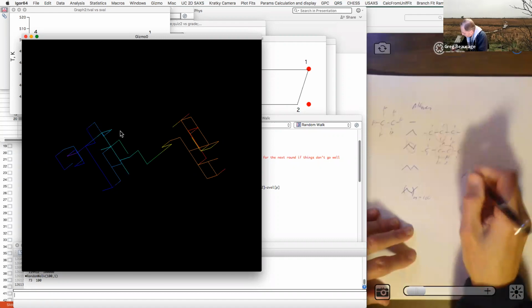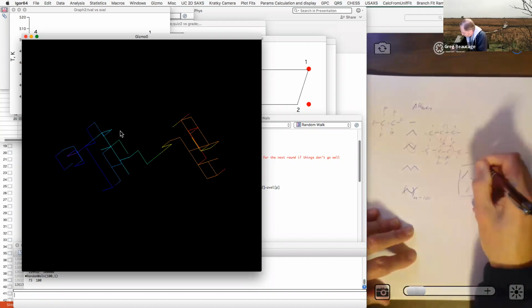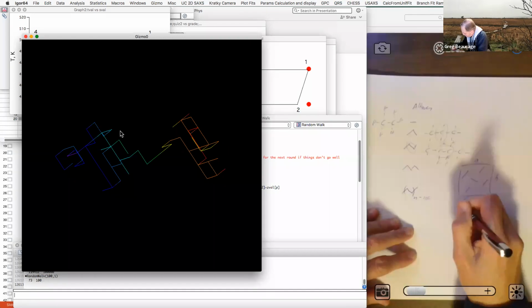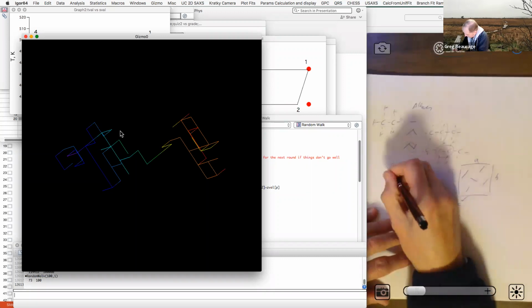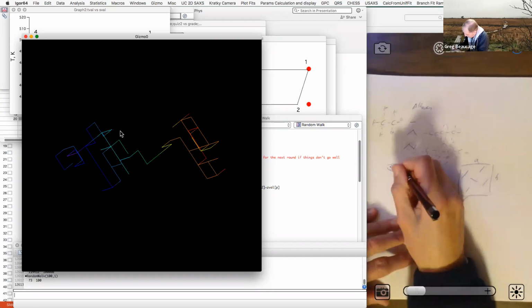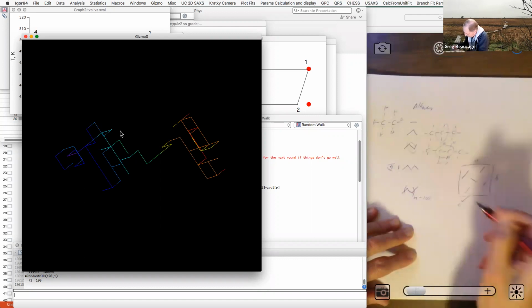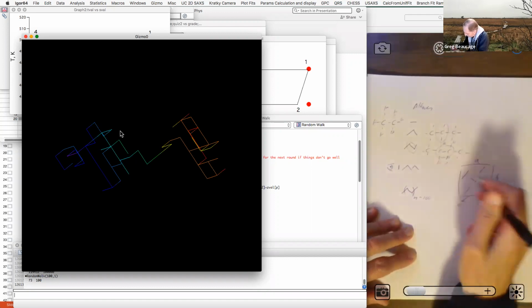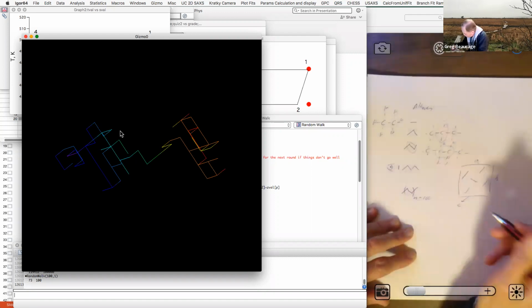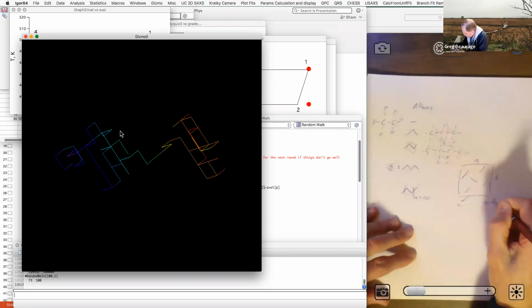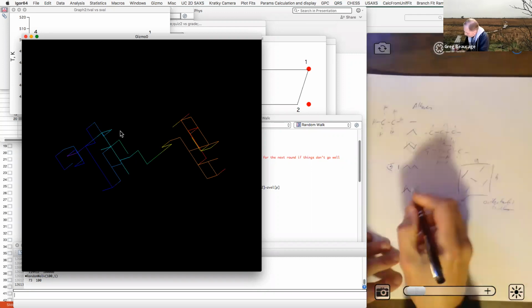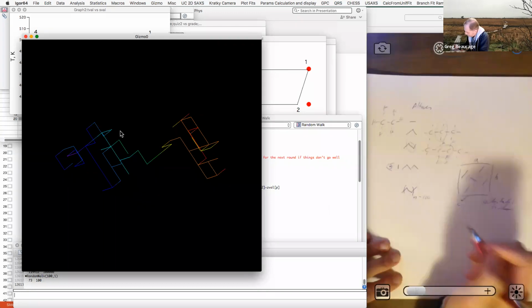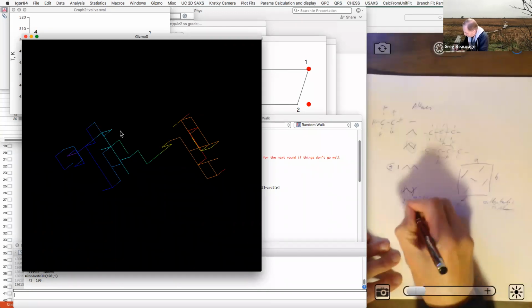So this is looking down the crystal lattice, and the AB, and the C direction is into the paper, which would be the chain direction. So like if you look at this thing this way, you see that this projects into a straight line. Each of these straight lines is one of these chains going in, and all the alkanes crystallize kind of in that way. It's an orthorhombic crystal. And so A, B, and C don't equal each other. And C is basically a unit, a monomer unit length, which is like 2.5 angstrom.